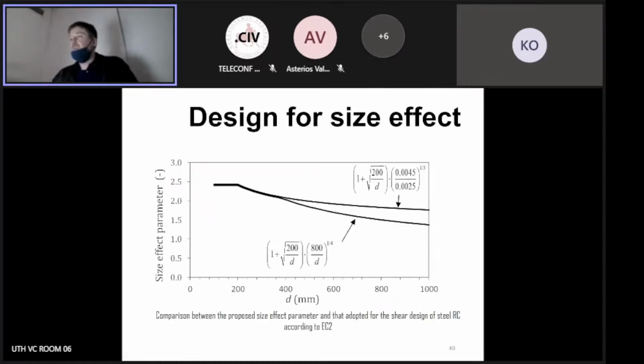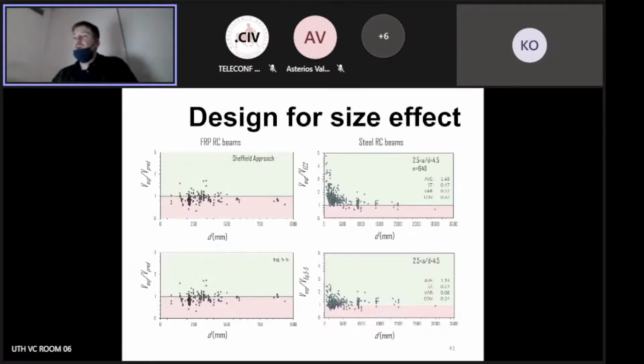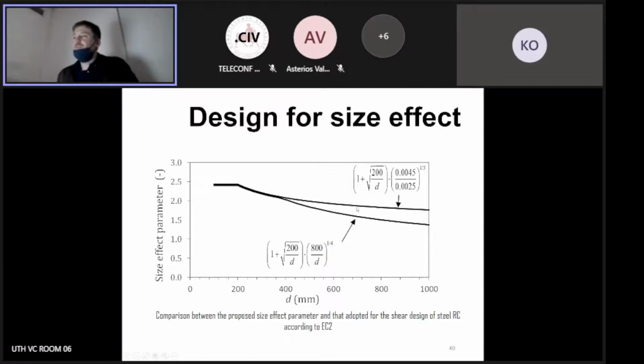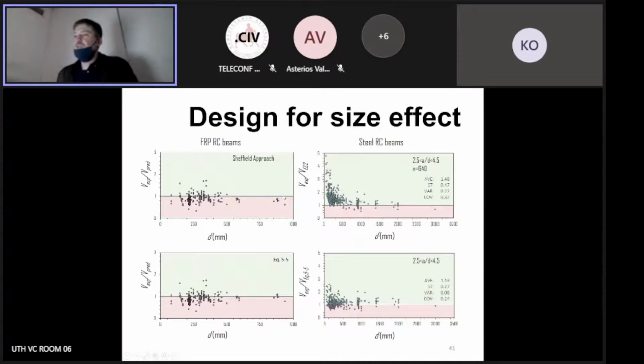And this can help to fix those problems that I showed you at the beginning. So basically what I did is, from the one on the top, that was already in the literature, placed in FIB Bulletin 40 as a provision for VC, for the contribution of concrete. I made it a little bit more pronounced, so to get all these guys, which we see here, a little bit up. So you see that applying that provision really helped to give those predictions a bit more accurately.